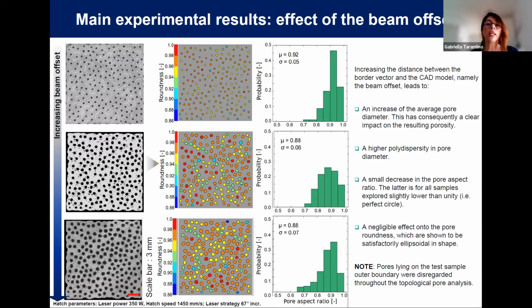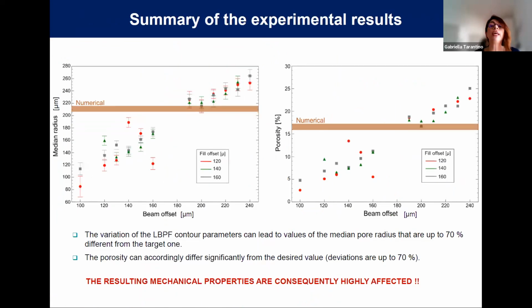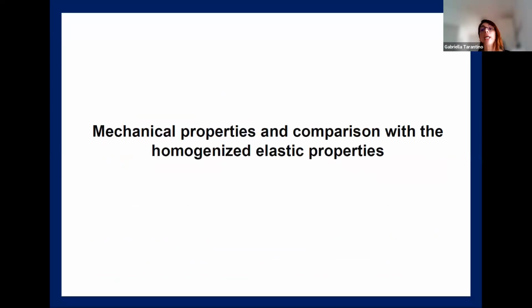Now, the visual result is clear. Of course, it has a strong impact on the final porosity, which can appear to be very different from the target porosity. And then we quantify, as I said, a campaign where we vary many other parameters like the fill and also the order by which the structures are 3D printed. We can see that porosity can vary by up to 70%. And that, of course, makes us think that there is a huge impact of this process parameter on the resulting mechanical properties, which we try to quantify next.